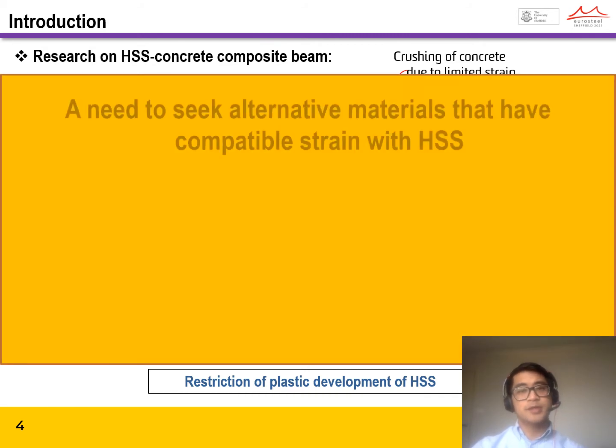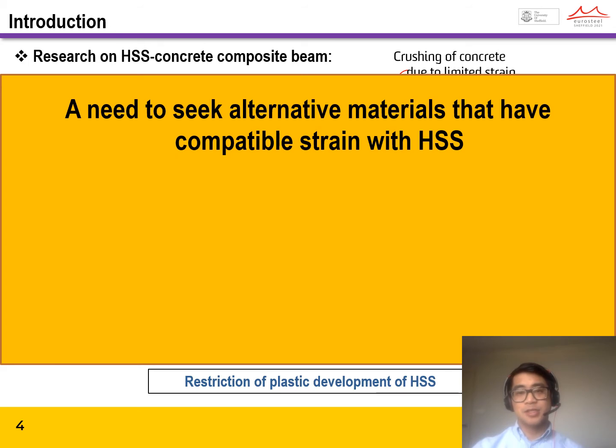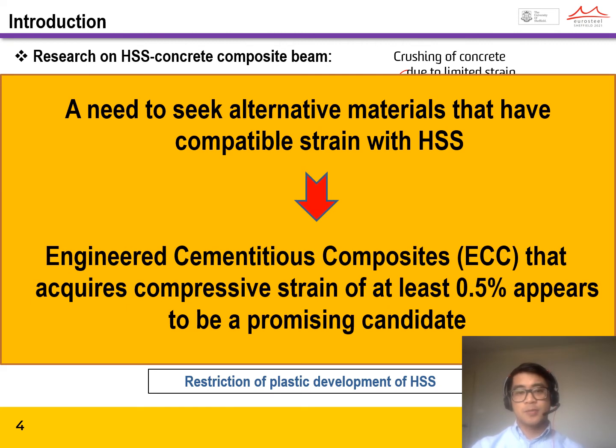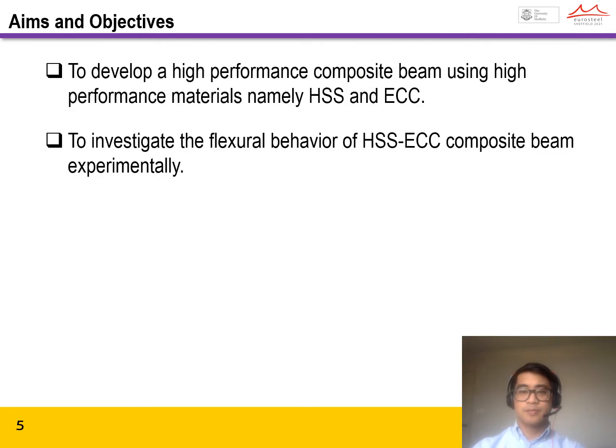Toward this end, there is a need to seek alternative materials that have compatible strain with high-strength steel. It has been found that engineered cementitious composites, which acquire compressive strain of at least 0.5%, appear to be a promising candidate. The aims and objectives of this research are, first, to develop a high-performance composite beam using high-performance materials, namely high-strength steel and ECC, and second, to investigate experimentally the flexural behavior of the high-strength steel ECC composite beam.